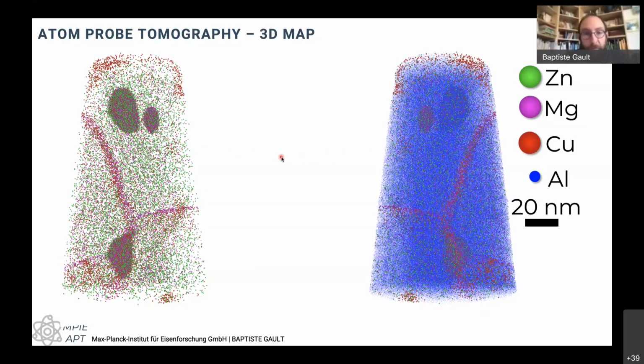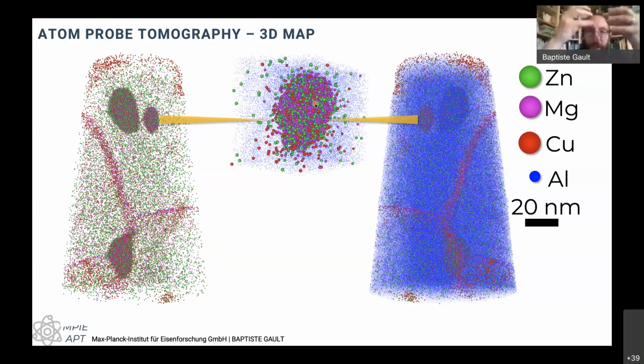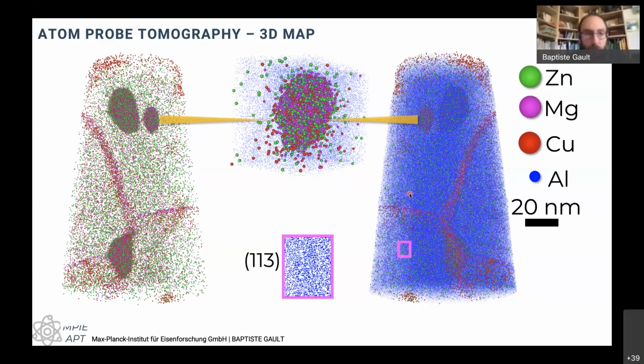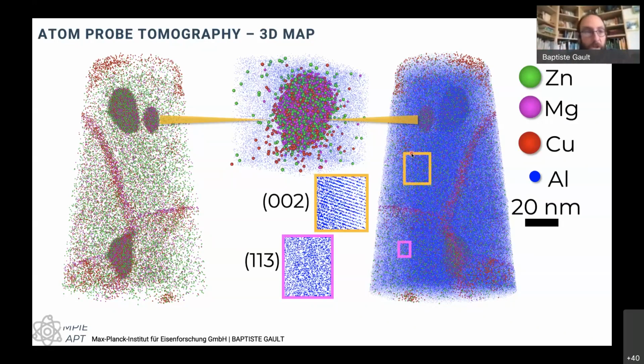It is a 3-dimensional map of composition. And so I can look at some of these precipitates in detail. I can try to measure the composition and the way the composition evolves near the precipitate and inside the precipitate. The thing is, sometimes, as I said, we need to assume that the atoms are coming in the right order. And when they do, which is most of the time actually, we have the resolution in the Z, in the depth, to actually image atomic planes. So in this grain, I can see some of the 113 planes, and here I can see some of the 002 planes. Because they're more or less superimposed within the data set, I can tell you that we had one set of planes like this and a second set of planes like that. So we've crossed the grain boundary. We have a lot of information there that we can use. I'll get back to this in the next few slides because I think it's quite an important feature.